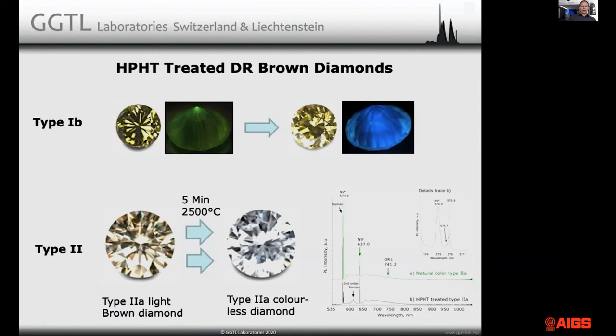So, if you take other HPHT treatment results, if you take a type 1B brown diamond and you HPHT it, it will turn yellow. If you take a type 1B olive diamond, you HPHT treat it, it will turn yellow as well. So these stones, same thing, their color, and even the orangey ones, you HPHT them, they turn yellow. All those color modifications in type 1B diamonds are all related to vacancy clusters, and all are annealed out by HPHT treatment.